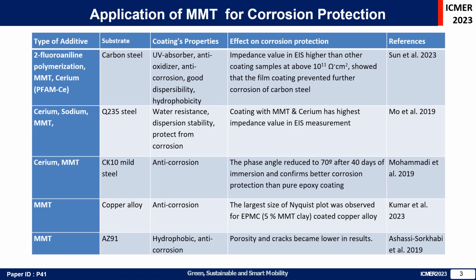Kumar et al. used MMT on copper alloy and their coating showed anti-corrosion protection properties. The largest size of Nyquist plot was observed for EPMC 5% MMT clay coated copper alloy.